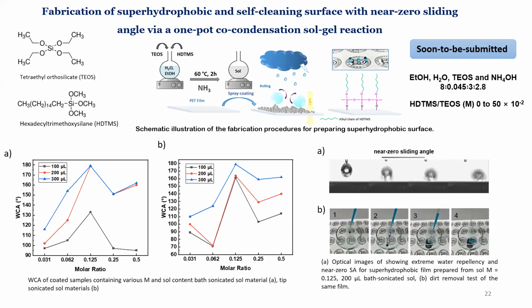No aging was needed. A specific amount of sol was taken. It was sonicated using tip or bath sonication in water, and then immediately spray coated on PET films. We observed that at a specific concentration of the sol, we obtained a superhydrophobic surface in which the droplets rolled and did not pin onto the surface, so we couldn't really obtain the water contact angle in this case.